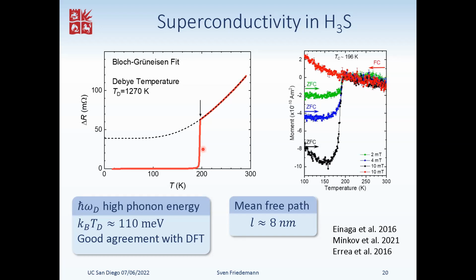But yeah, there is reasonable uncertainty, because in order to extract the electron phonon coupling, we need to take into account the geometry of the sample. And of course, there's always a reasonable uncertainty in the thickness of the sample, because we can't really measure this. We can only guess this based on what we think is happening under pressure. And hence, there's easily a factor of 2 uncertainty on the electron phonon coupling if we were to extract it just from the resistance.